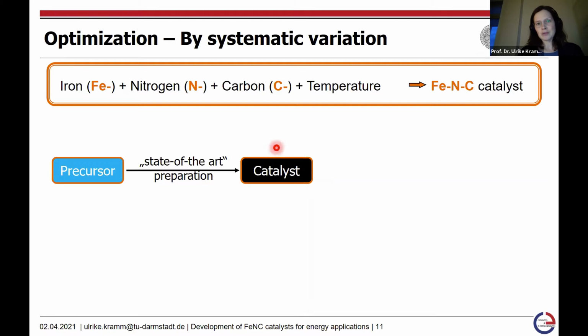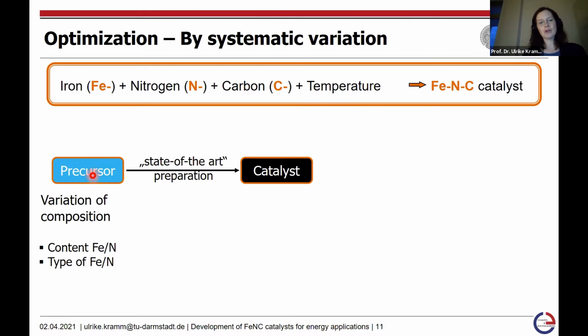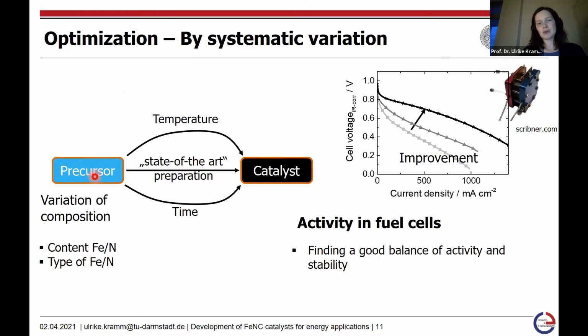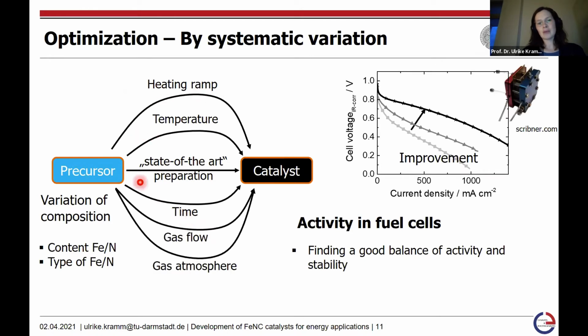When you would like to optimize your catalyst preparation, let us assume you have a state-of-the-art preparation approach. There are different ways you can optimize it, for instance, by a variation of the composition, the temperature, the time, the heating ramp, the gas flow, the gas atmosphere. All of these different factors during the heat treatment will affect the performance of the final catalyst material, as, by the way, does the acid leaching that we perform. The aim is, of course, to get an improvement.